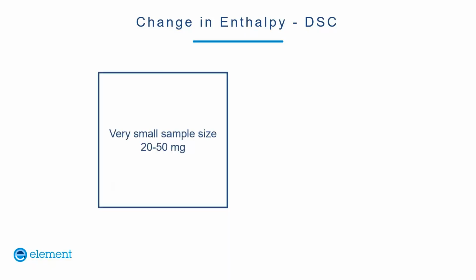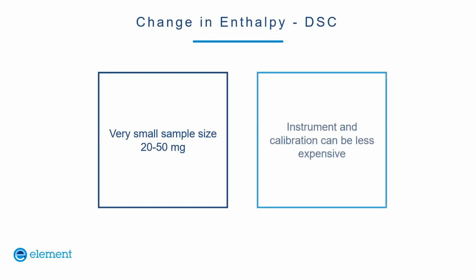We can also measure change in enthalpy, and we do that with a DSC, a differential scanning calorimeter. A small sample is heated, and the amount of energy required to heat the sample is measured and compared to an inert reference material. Because the glass transition temperature creates a change in properties of the material, the polymer chains reorient, which requires a change in energy to heat. And this is shown as an inflection point on the curve. Some of the advantages are, again, the instrument is less expensive than a DMA. Calibration can be more straightforward.